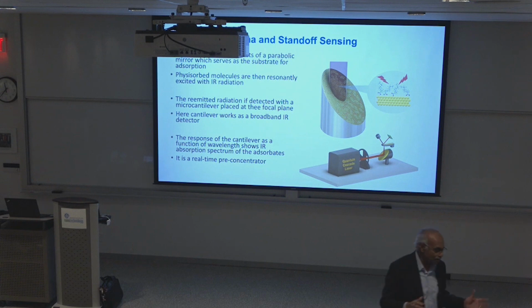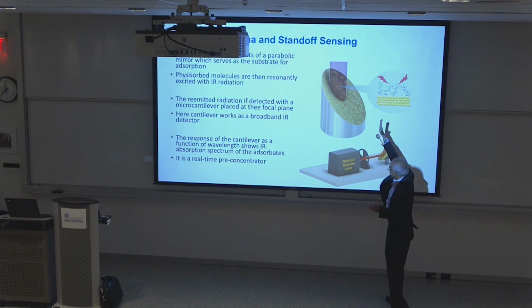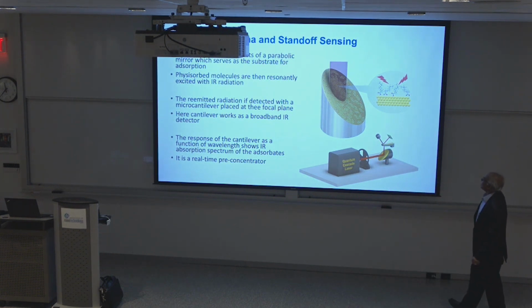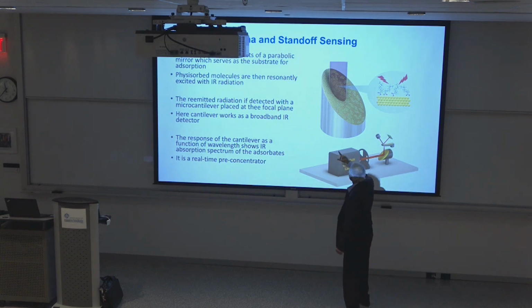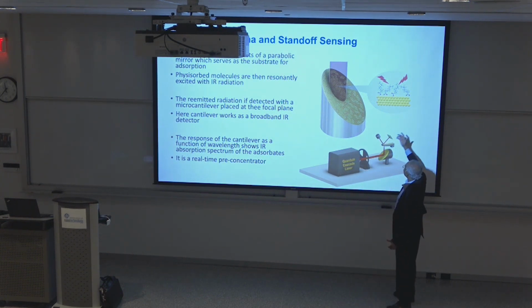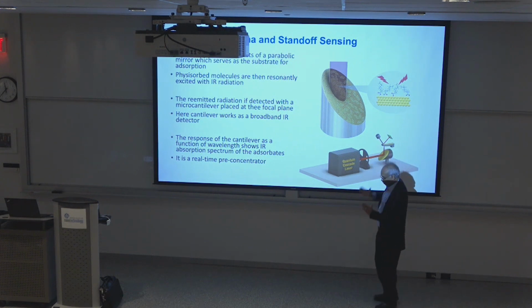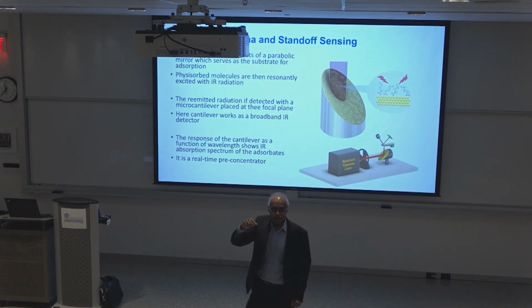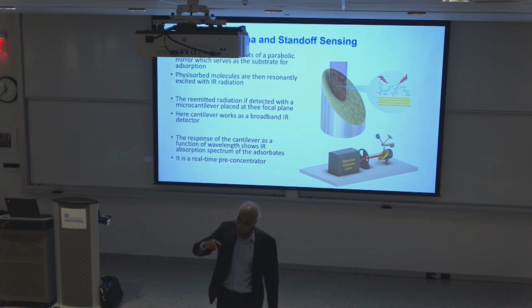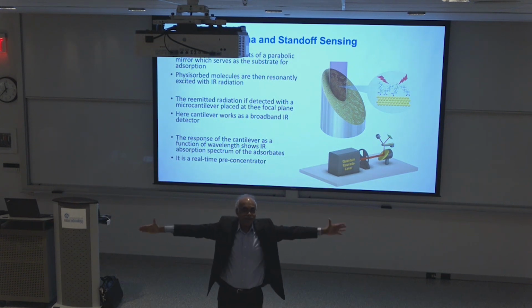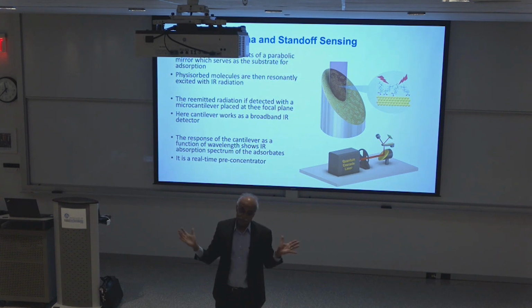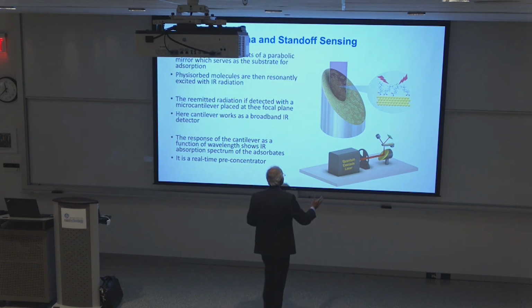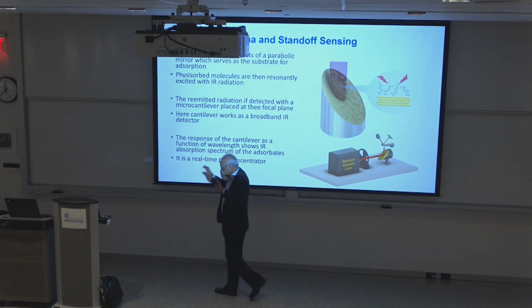So if we have, say, an off-axis parabolic dish, and let the molecules absorb on it, and we excite the molecules with infrared light, the light is then focused to, for example, the focal point. We can actually use a cantilever, the optical beam detection system. So you could be sampling a whole area. Your nanosensor is supposed to be a physical sensor. Yes, it's a physical sensor, but all the chemistry, the absorption, is happening somewhere else. So we separate the absorption area from the sensing area. And this was an excellent concept.